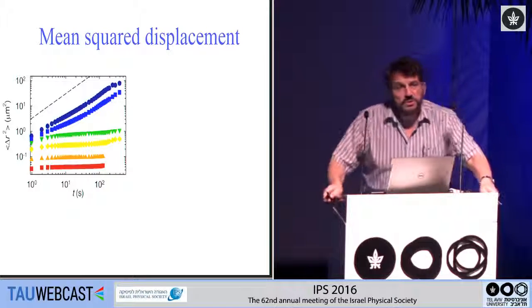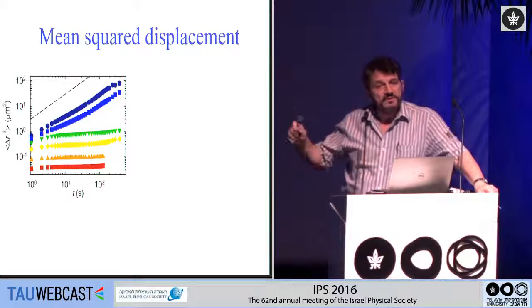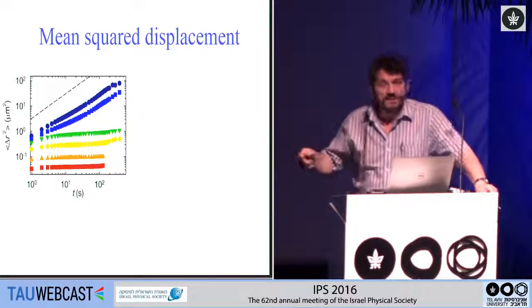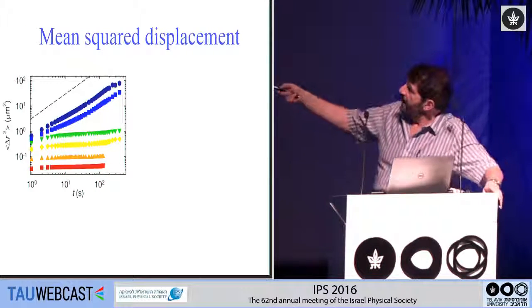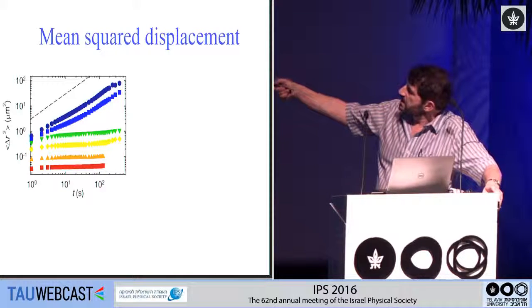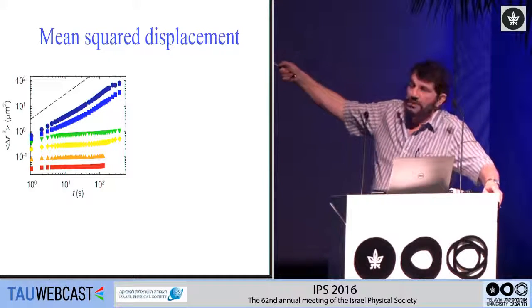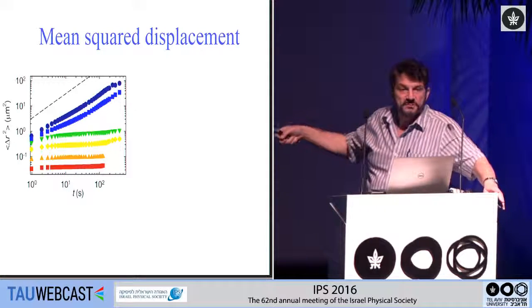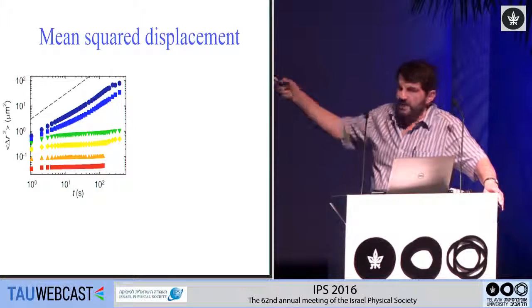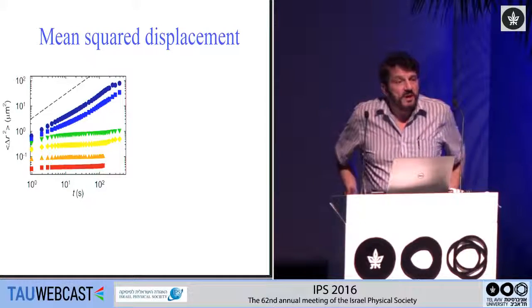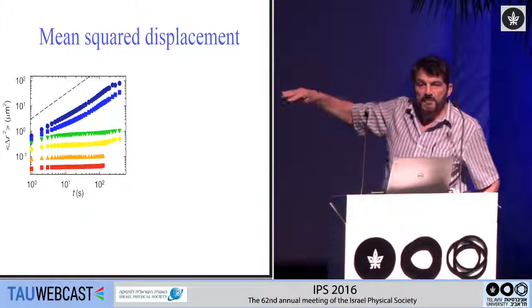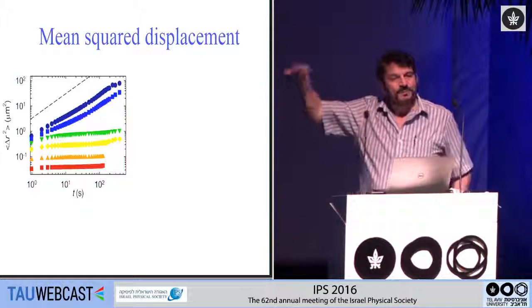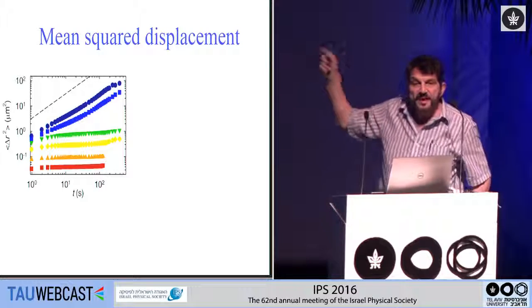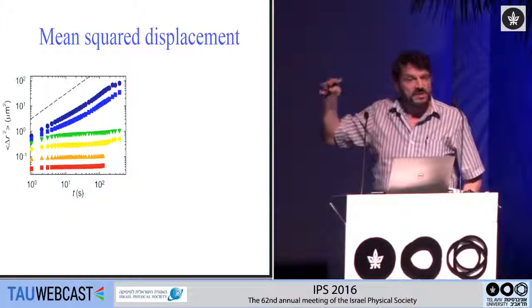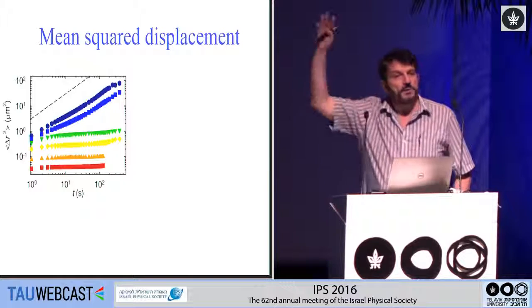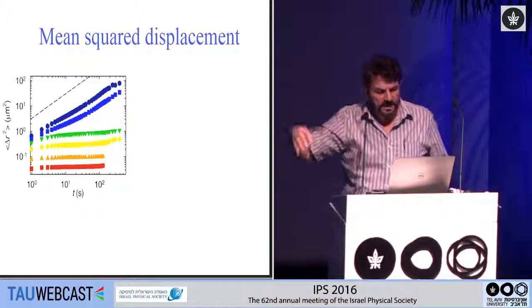So the first thing that you can do is just measure the fluctuations of the particles, measuring the mean square displacement of each of the particles. And if you ensemble average, if you look in the fluid, you see that the mean square displacement increases linearly with time. It's essentially diffusive motion. And there's a transition where the mean square displacement no longer increases with time, but rather is fixed in time. It doesn't change with time, and that's consistent with the fluctuations that we saw. Nevertheless, there are clearly fluctuations. They just don't change in time. And that's what we saw. The particles remain fixed in position, but they fluctuate a lot in time.